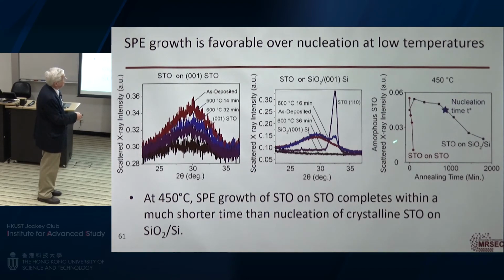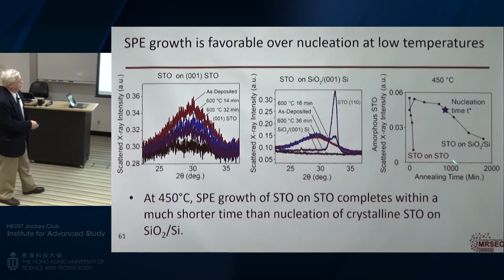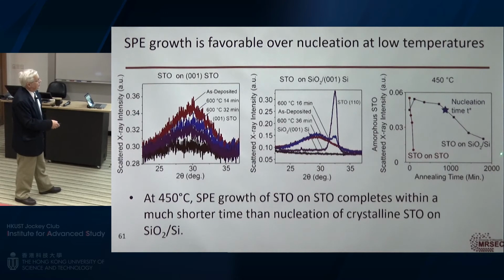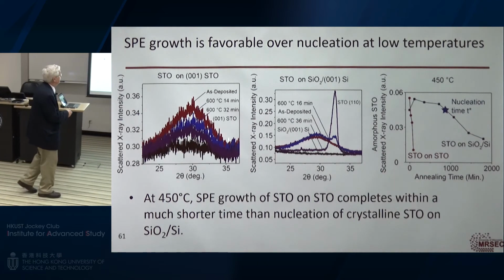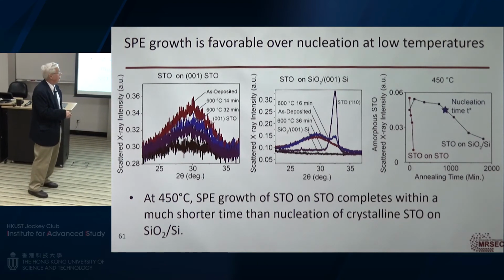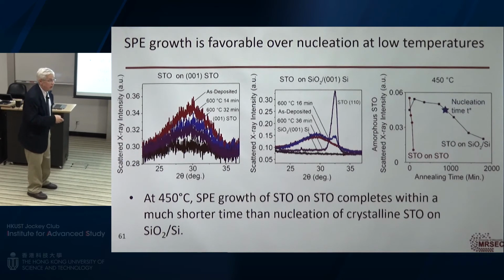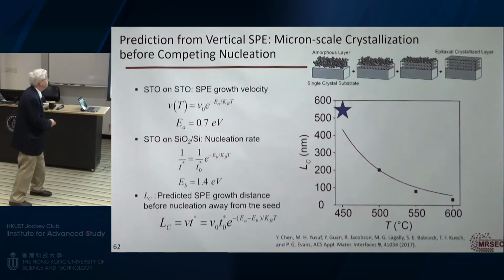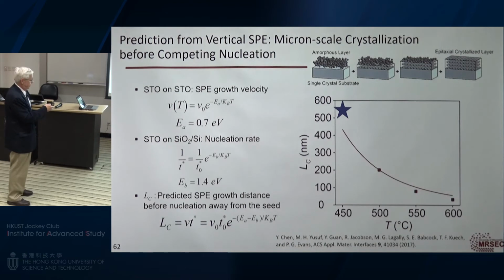And what's shown here is how fast it crystallizes, whether it's on an epitaxial substrate or single crystal substrate, or on an amorphous substrate. And you can see it takes 1,000 times longer, a factor of 10 to the third longer, to nucleate on an amorphous substrate homogeneously than to epitaxially grow. So that means if I put an amorphous material on a single crystal substrate, it'll epitaxially regrow, and it'll grow a long distance. And that's what's shown here.